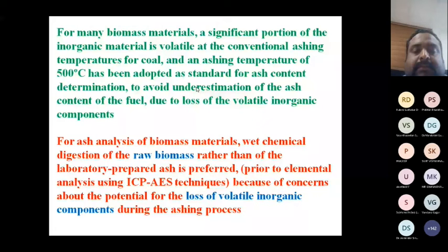Whereas an ashing temperature of 500 C has been adopted as the standard for determining the ash content of biomass, to avoid underestimation of ash content due to loss of volatile inorganics. If you ash biomass at 800 degrees, some of the ash may become volatile and escape. So you will not measure the real ash content of biomass at an ashing temperature of 800 degrees. That is why for all biomass fuels, the ashing temperature should be around 500, in order to avoid the loss of volatile inorganic compounds.